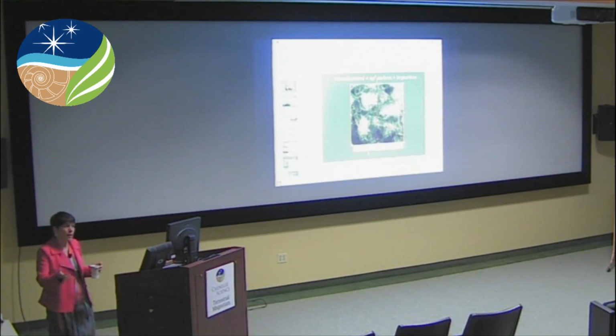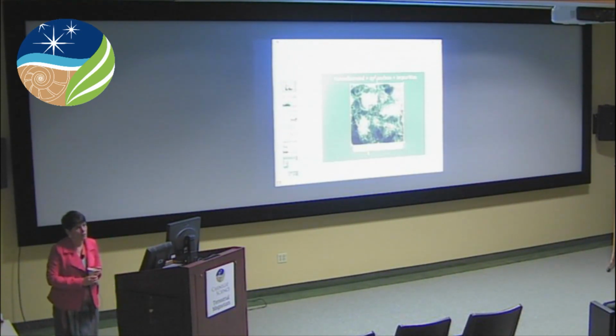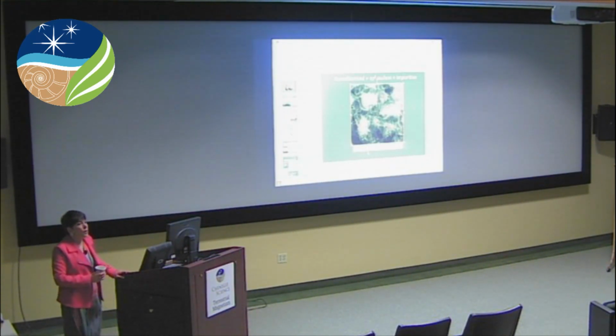People have started to look at this in bulk silicon and other impurities. With a 200 kV beam, you can steer an antimony around and so on. I think that these are simply physisorbed impurity silicon for the most part on the surface. It's room temperature, so we like to think, at least I do, naively, that things are mostly fixed in place at room temperature and you have to heat them up for stuff to move around. That's not true on the surface. Real surface scientists will tell you there's all kinds of crud moving around all the time at room temperature. We just don't usually get to peek at it.